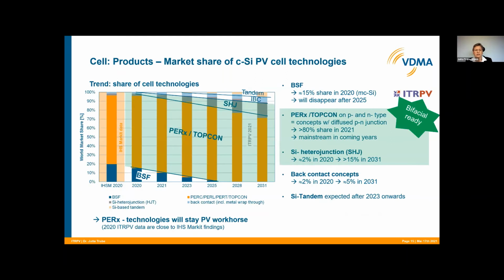So how will the crystalline cells develop in the future, and with which technology? As I said, the PERCs, including TOPCon, are still the workhorse. It is more than 80% of the market, and this will more or less continue. The old aluminum back surface field will disappear in a few years, by 2025 at the latest. And the silicon heterojunction will increase to about 15% in the next 10 years. Also the back-contacted concepts and tandem will appear. Tandem may come on the market around 2023 onwards. And all these green marked areas, TOPCon, PERCs and silicon heterojunction, are technologies which are bifacial ready already.